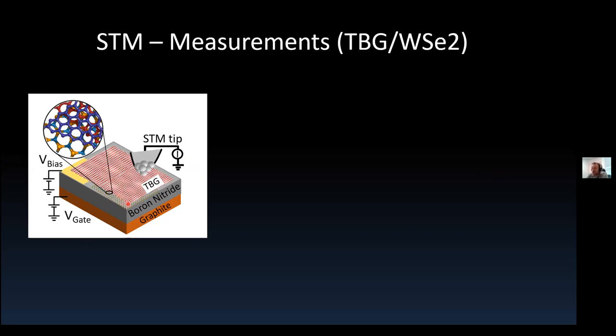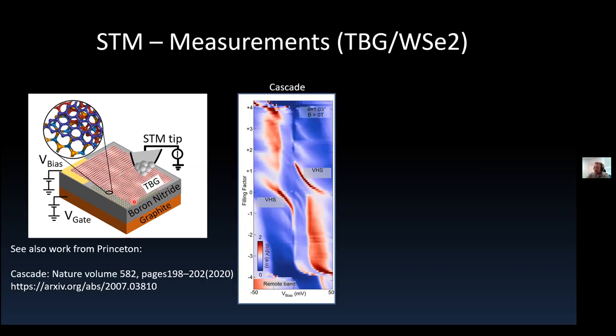And what we did very recently is we tried to incorporate our technique of having tungsten selenide below this twisted bilayer graphene, and having graphite gates. So this is a slight modification of our scheme, where we introduced tungsten selenide as an immediate substrate to the twisted bilayer. And immediately things became clearer.